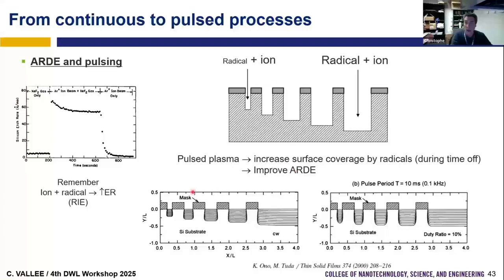And this is an example of how you can improve aspect ratio dependent etching. Aspect ratio dependent etching happens because, depending on the aspect ratio, we don't have the same number of radicals going in the trench. And since we don't have the same number of radicals, we don't have the same etching rate depending on the aspect ratio. So when you have high aspect ratio, usually you have slower etching rate compared to low aspect ratio. But now if you pulse, you can play with the pulsing to try to compensate. And during the off time of the pulse, you will have more radicals than ions. So you can compensate here and try at the end to have no aspect ratio dependent etching. So whatever the feature, high aspect ratio or low aspect ratio, you etch at the same etching rate.